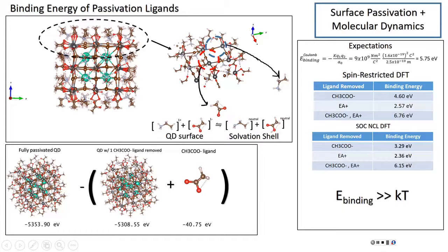So just looking at this top surface, altered it a little bit, you can see it took one of the acid groups off from the centralmost, because it's least affected by other ligands, so you can get a better idea of just removing that ligand without any correlation effects from other ligands. And then I also just removed an amine that's adjacent to it, that's covering one of the faces.